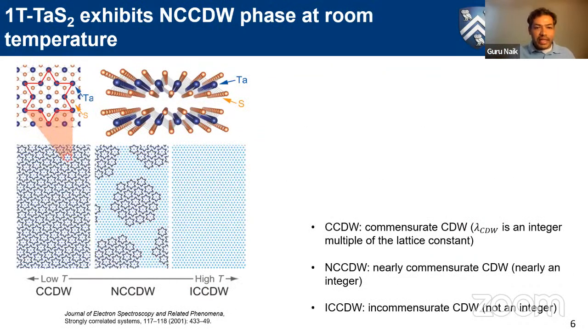So why tantalum disulfide? I'm an experimentalist, so we need to think about how I can make this material, how I can probe this, etc. That's what really led me to tantalum disulfide. One of the coolest parts about tantalum disulfide, first of all, is that it's 2D, which means I can pick a crystalline 2D material and then simply exfoliate layers from this, multiple layers.